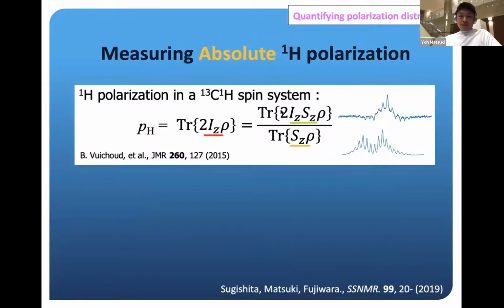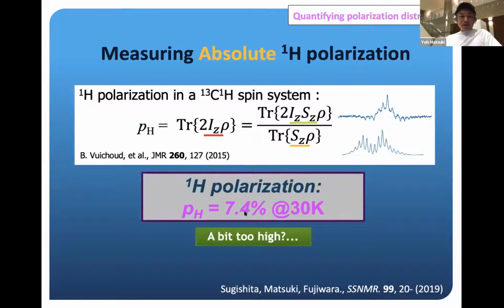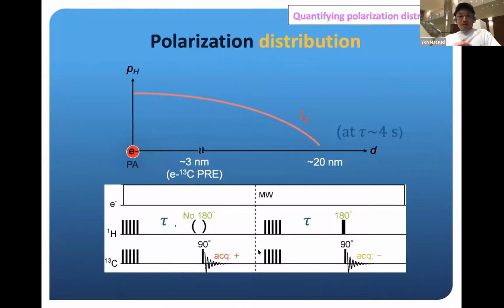Subsequently, we also noticed that by just taking the ratio of this spin correlated term to the Zeeman order term, this directly tells you how many percentage of proton polarization you have in your sample. And we did that, we found 7.4% at 30 Kelvin, which is pretty high, kind of too high, or at least a little higher than we expected in the beginning. But soon we realized that this experiment is not like evaluating polarization level averaged over the whole sample or anything like that. Because this is what's happening.